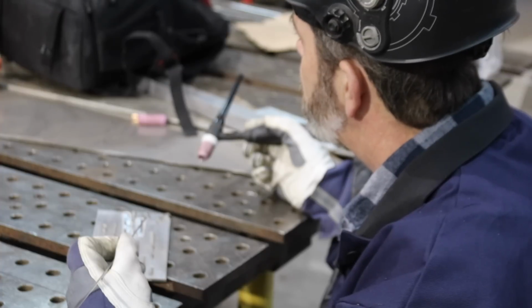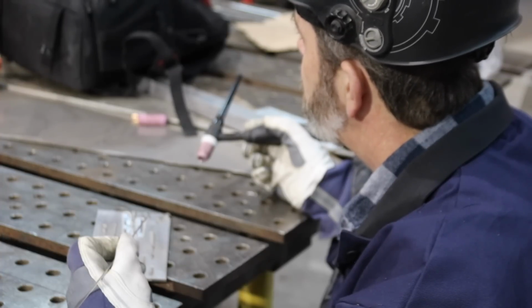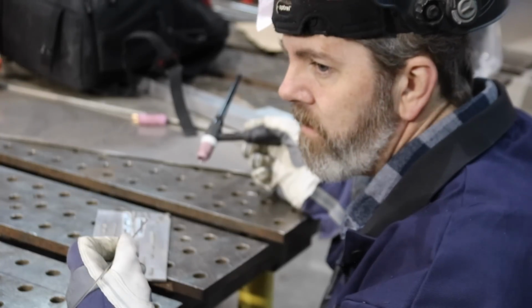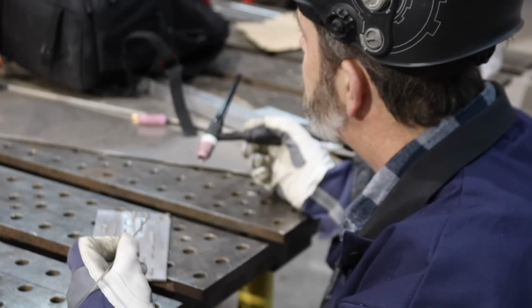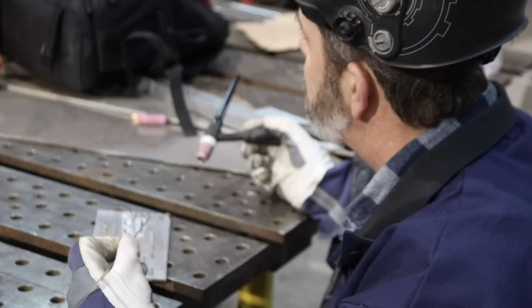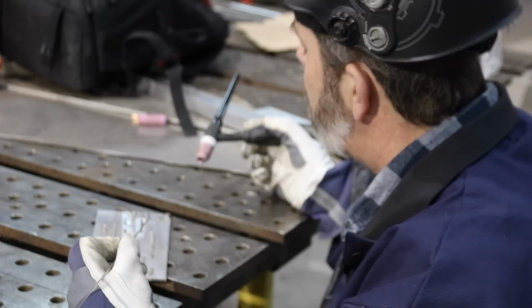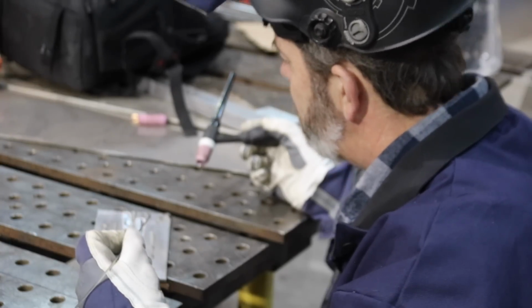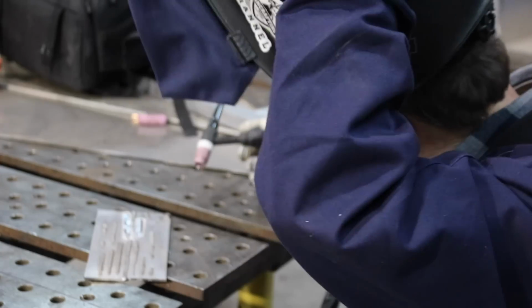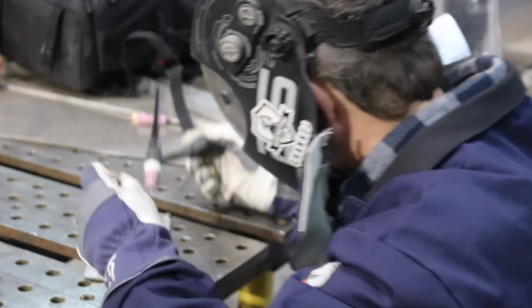After you ran a bead or two, the whole thing would start to get warm and it would take less and less amperage. Like right now, you're set on 120. When that piece was cold, I probably needed all 120 to get my puddle going. You're probably only running 100 amps now. I'm going to see what it's reading out when you run the next one. But that was a good one. Whatever you did there, do it again.